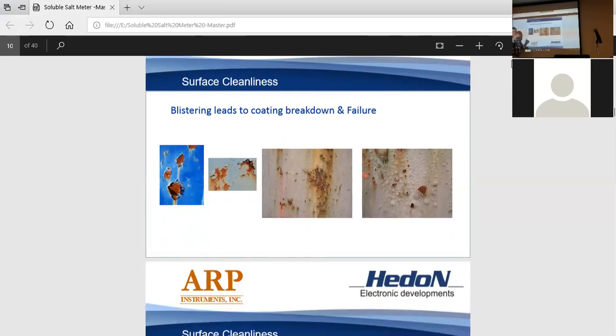If the ballast tank top, say, is not in immersion, you'll get some pretty serious corrosion in the ballast tank tops. And when you do inspect tanks like that, you'll see massive corrosion around the edges, weld seams and all that. That's because the coating's real thin at those areas, and that's the first area to be compromised.